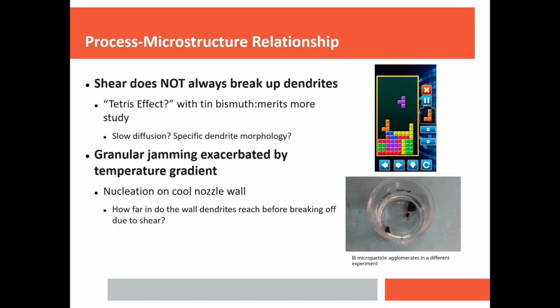I mentioned that a little bit with the zeta potential thing earlier, but additionally, if this nozzle is cooler than the metal that's coming out of it, you may have nucleation on the nozzle wall. So can you choose your material for the inside of the nozzle wall such that those dendrites don't bond strongly to the wall and are broken off by the fluid flow? Is that possible? Can you alter your nozzle geometry as well to aid that process? So those are things to think about, as well as the zeta potential stuff I mentioned earlier, the analogy to zeta potentials at least.